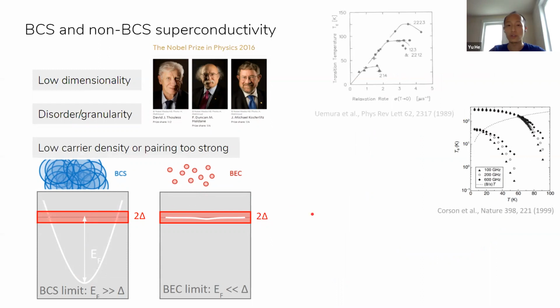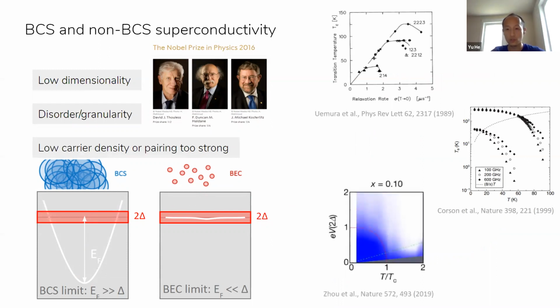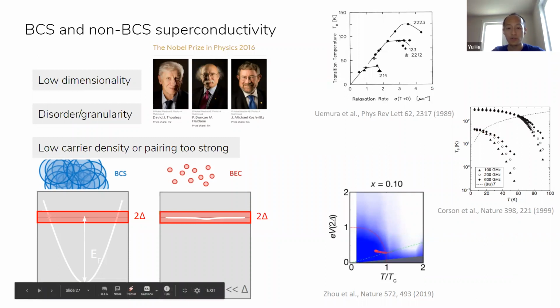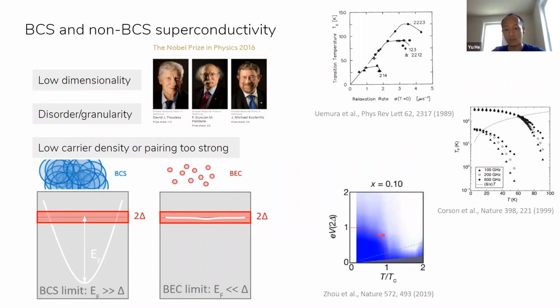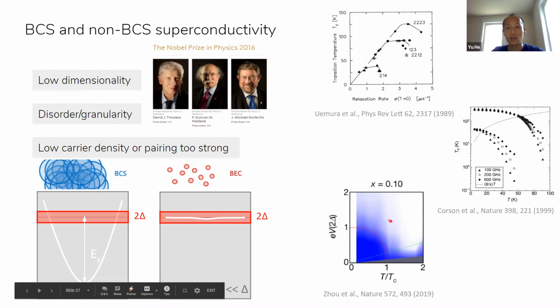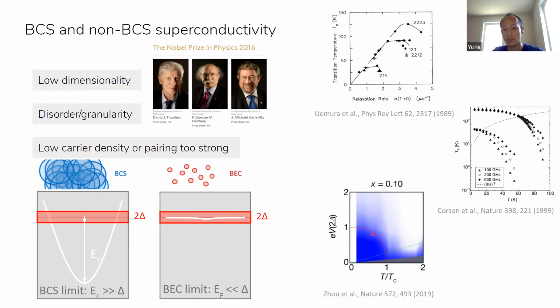Actually, in cuprate superconductors, especially the underdoped cuprate superconductors, measurements of superfluid density with muon resonance or with optical reflectivity, or very recently from the very own physics department of Rice with shot noise, people have observed signatures of strong fluctuating superconductivity and low phase coherence in those underdoped to even optimally doped cuprates.